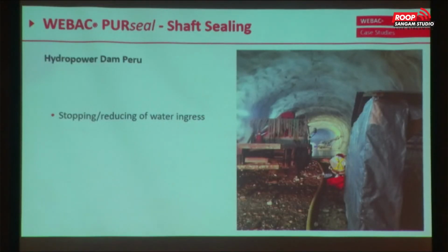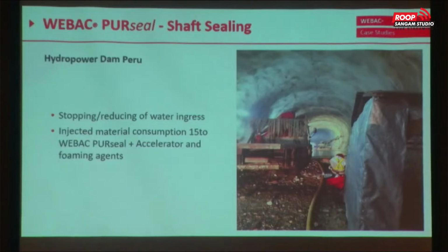We sent over material because the target first was doing some strength repair or consolidation in front of the shield of the tunnel face. We went there and they came up and said, look, you are here, but we have a little bit of a water problem. Can you come visit and see what we can do? And they shifted us to that point, and at the end they want to do waterproofing. Lucky that we had the toolbox with us. So at the end we injected roughly 15 tons of the polyurethane resin, including accelerator and foaming agent.